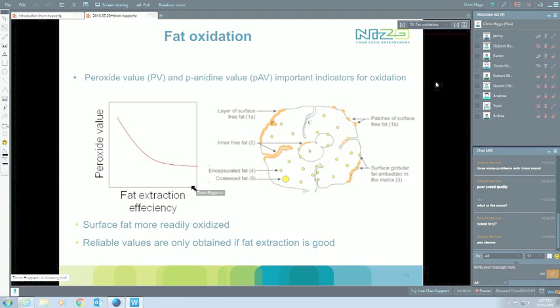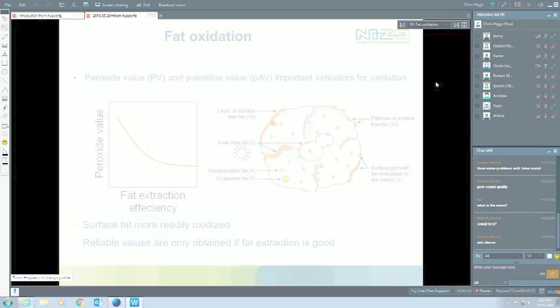Whereas if your fat extraction is good, you get all the fat out, so you also get all the fat in the internal out of it. That's when you get realistic peroxide values, you get realistic oxidation indices, because it's that surface fat that will cause the problems, that will oxidize readily, and that will give you issues there.